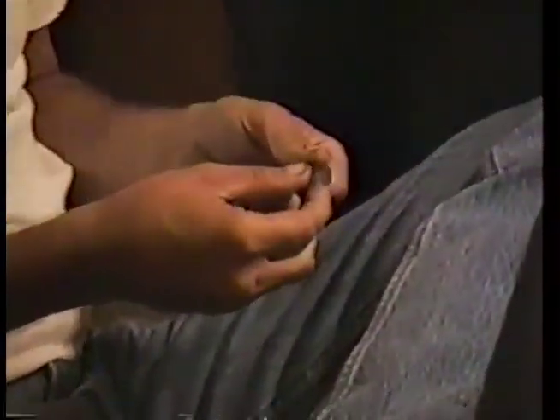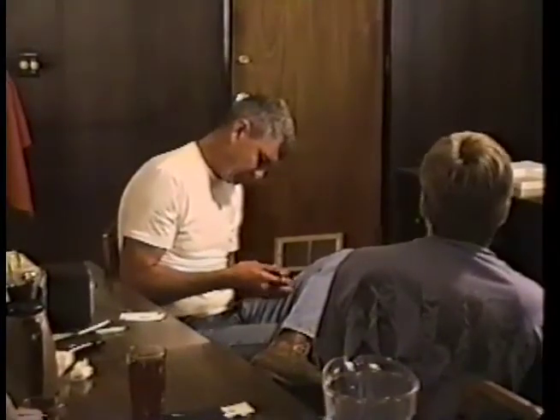I'll pass this around, you can look at it very closely. What we look for is the chrome actually adhering to that surface, hanging on to that surface, where as much pressure is exerted to crack that off. You look at the formation of the way it cracked. And you'll see that's a water jacket side of that particular liner. And then we rate them from poor, fair to good to excellent. You can see the difference here, particularly in this area. The black lines there being the chrome, and it did not adhere to the base metal in that situation. Here it tried to, but it did not completely adhere. And here there's very little distinction between the chrome layer and the cast iron boundary when it's fractured away.